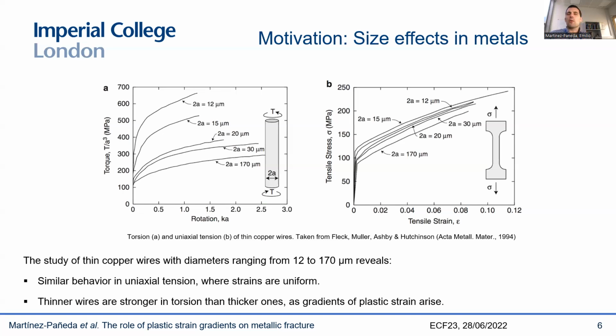And there's a very wide range of experiments, particularly at the micro scale, that show that geometrically necessary dislocations or plastic strain gradients can increase the flow strength in metals. But I'm going to illustrate this concept with this set of experiments by Fleck and co-workers on thin copper wires, because they're really clean and beautiful, in my opinion. So as you can see here, they tested very thin copper wires of different diameters under both uniaxial tension and also in torsion.